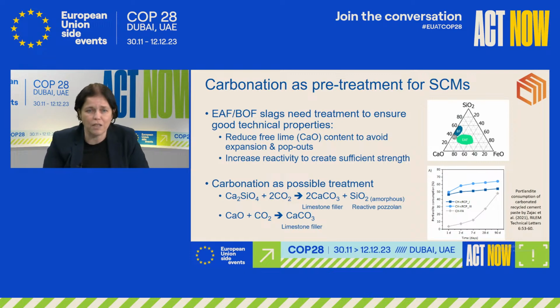And carbonation is actually a good treatment to do both of these things. So we can react the calcium oxide with CO2, producing a limestone filler, which no longer has these dangers for expansion. And also reacting the calcium silicates that are present with CO2 leads to also this limestone, but also an amorphous silica phase that is a reactive material that can have pozzolanic properties, and it has been shown indeed that this can be sufficient to have the desired reactivity you need for a cement.